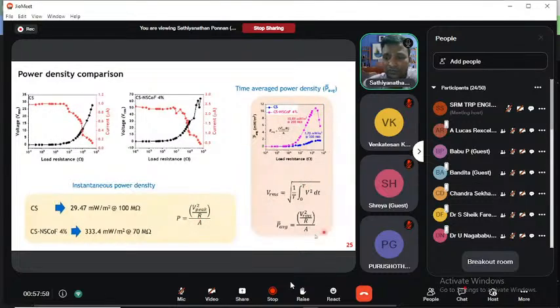So we followed another equation, and we calculated the time average power density, which you can relate to the AC signal which we get in our house. So you can connect this power with these things. Using this equation, we observed our chitosan system produces 1.70 milliwatt per meter square, whereas our composite system produces 10.89 milliwatt per meter square.